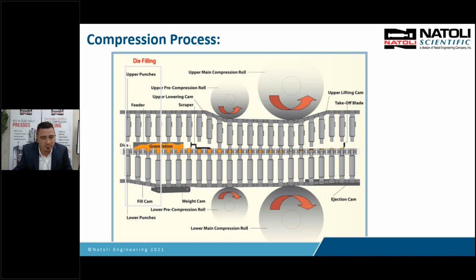And you'll notice in this image, as the fill cam pulls the lower punch down, there's granulation going into the die cavity. There are a lot of older machines out there and even newer machines that are designed like the old model where the fill cam is pulling down before it gets to the opening of the feeder. So what it's doing is pulling in air. Now the die and the lower punch come underneath the feeder and hopefully your product flows well enough that it goes into the die.